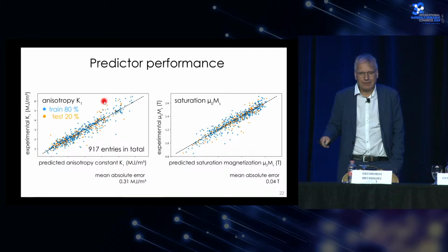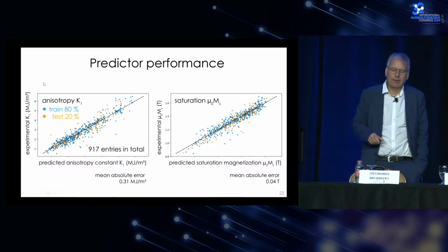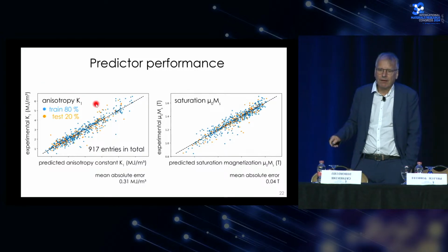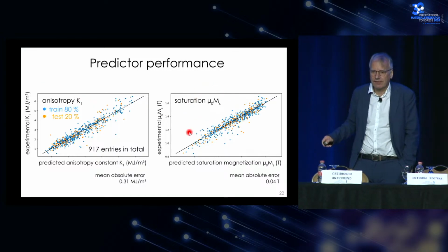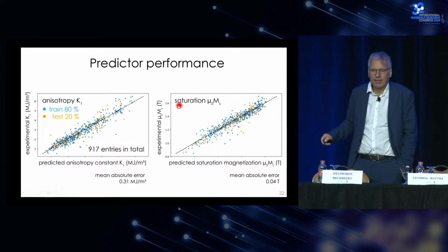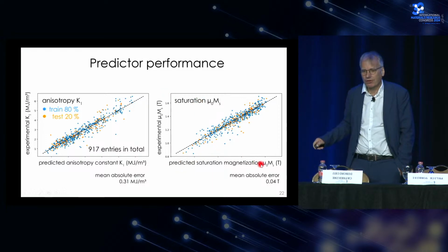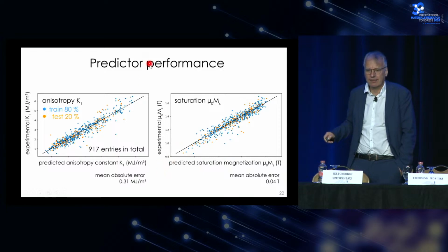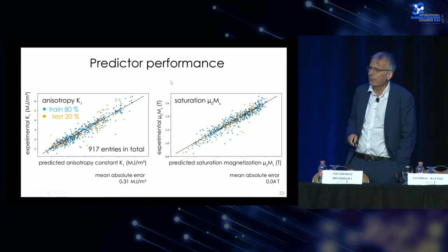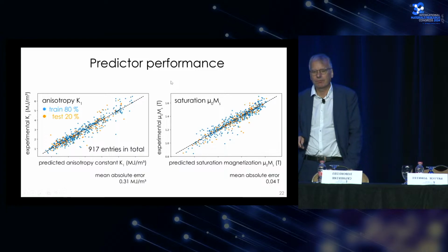And you see we have this almost straight line, and the mean absolute error is less than 10% of the absolute value. We can do the same with saturation magnetization. Again, we have the plot of the predicted saturation magnetization against the experimentally measured saturation magnetization.